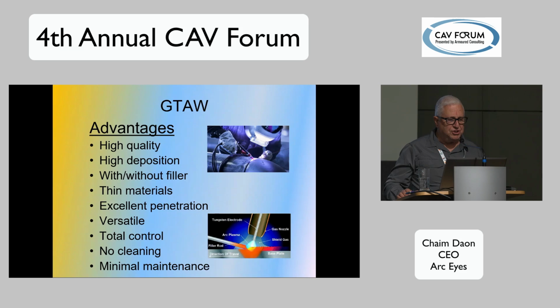We have high deposition. High deposition does not mean high speed. It means that the welding rod material that we're putting into the weld is fully deposited. There's no spatter like you see in movies, with the spatter going all over the place to make the action movies more exciting. All that spatter is weld metal that's being rejected from the weld pool.